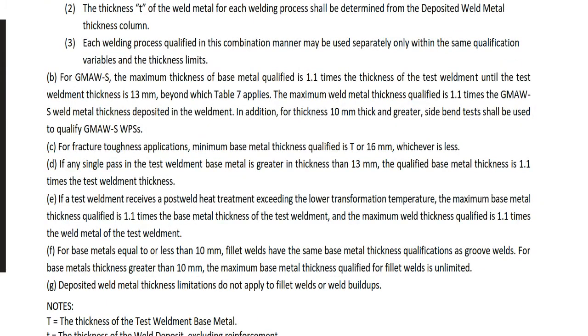D, if any single pass in the test weldment base metal is greater in thickness than 13 millimeter, the qualified base metal thickness is 1.1 times the test weldment thickness. Single pass, the test weldment base metal is greater than 13 millimeter. What it means is here.